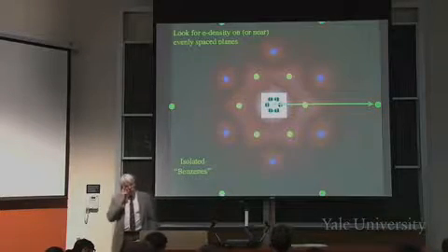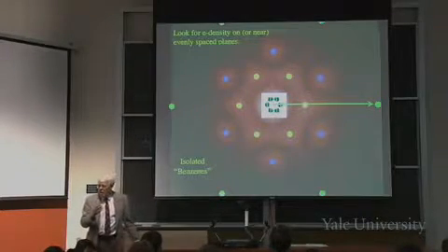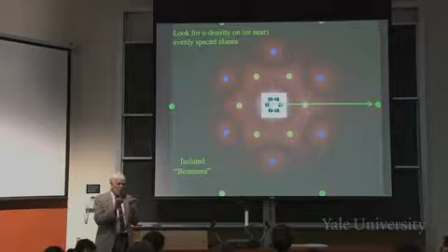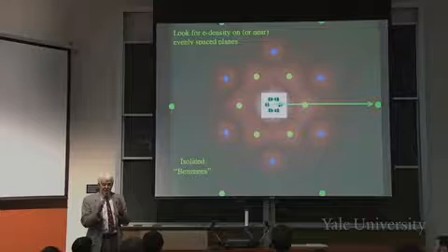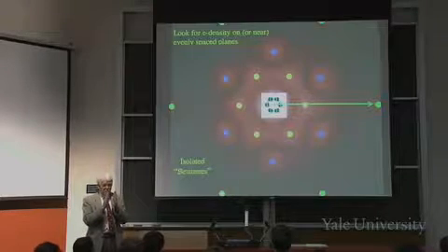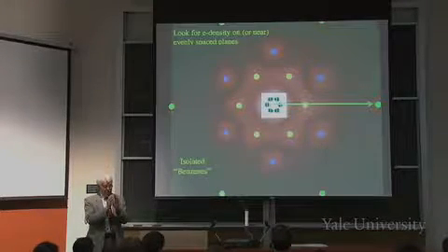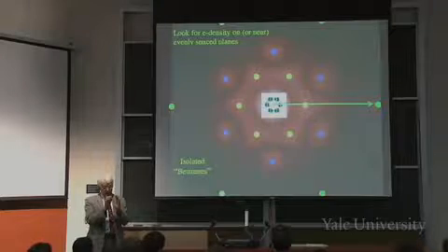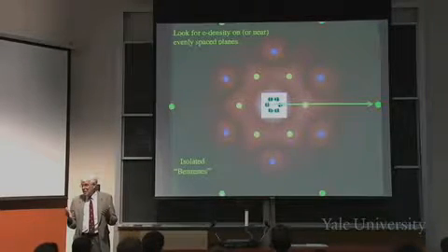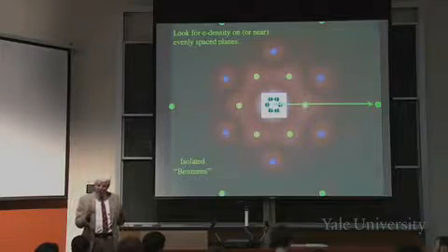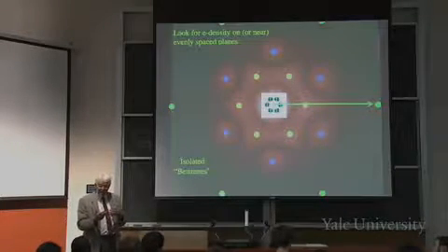Now, notice those ones far out are very weak. That's because although the centers of the dots lie right on the lines, the lines are getting so closely spaced that there's part of the electron density that's not right on the lines that in fact gets out to almost halfway between the lines, right? And that part of the electron density will be canceling.